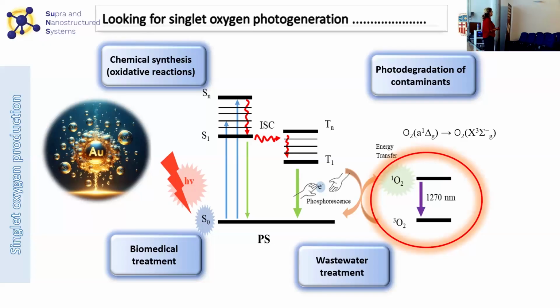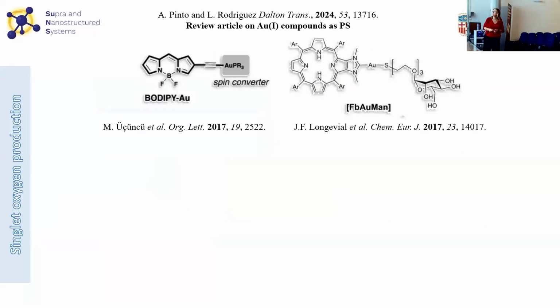establish the protocol in our requirement to detect the emission that is very weak. So it was not easy, but at the end we managed to detect the emission of the singlet oxygen that is at 1,270 nanometers, more or less. So once we detect this weak emission band, it is a direct correlation that our molecule is producing this singlet oxygen. At that moment, when we started with that, there were only, as far as we know, 2 examples in the literature about gold complexes displaying singlet oxygen, that are these molecules here presented.